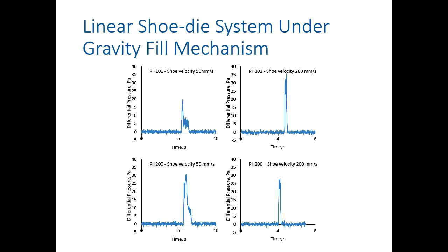We measure the differential pressure inside the die, and it proves the theory that as the experiment starts, we see a large increase in the differential pressure inside the die, and as the experiment continues, this pressure dissipates before going back to zero when the experiment is completed.